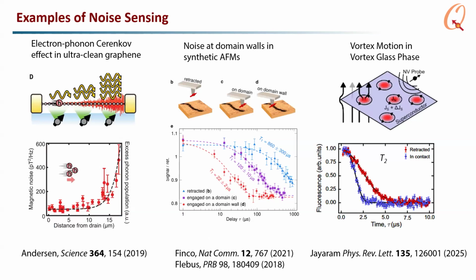So people have used this for a variety of effects, including measuring the electron-phonon Cherenkov effect in ultra clean graphene, where they see the noise actually gets greater as you get farther and farther from the contact. And that's just due to the fact that the electron drift velocity in these ultra clean devices is faster than the acoustic phonon velocities. So you get sort of a sonic boom of phonons, where it builds up along the direction of the current.